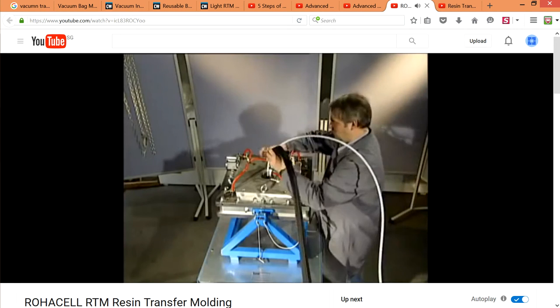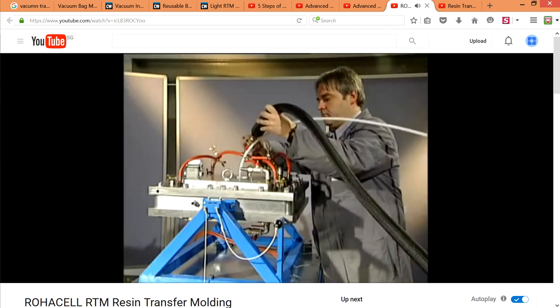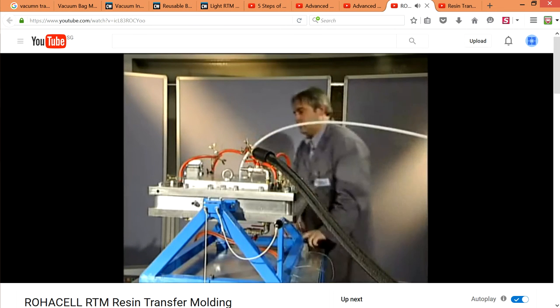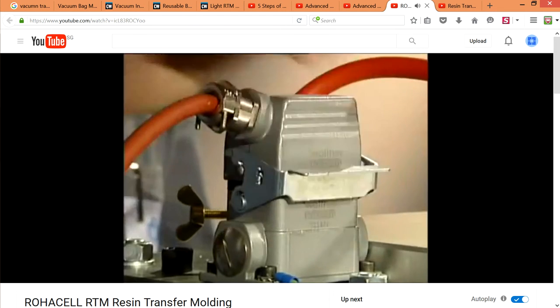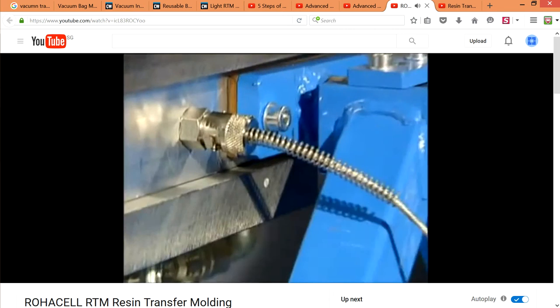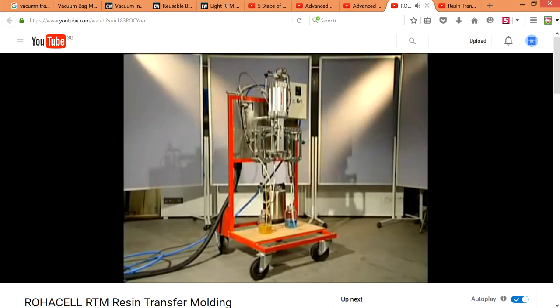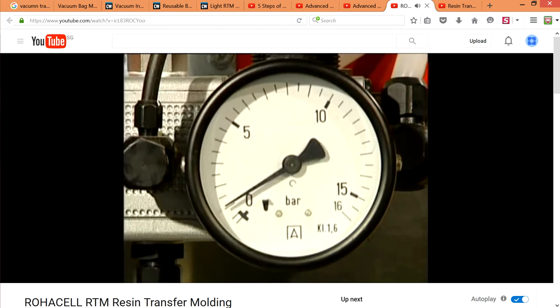Finally, the connections for resin injection and heat supply are attached, and sensors are positioned to control the mold temperature. With its excellent mechanical and thermomechanical properties, ROHACELL can be processed with all commercially available resins at extreme pressures of up to 6 bar or 90 psi. The injected resin impregnates the fabrics and adheres them to the core.